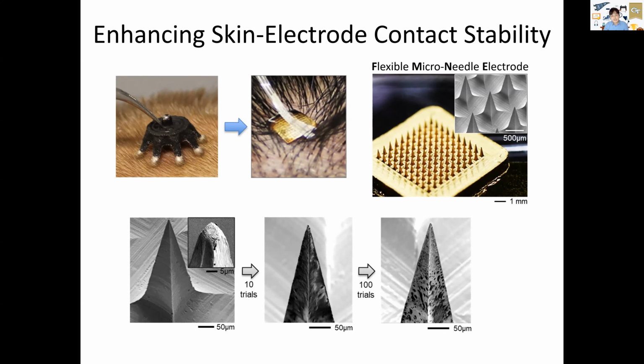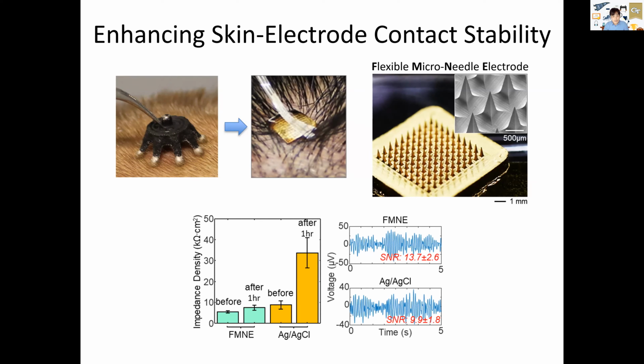And this microneedle can be reusable multiple times to measure EEG. The main advantage of this microneedle electrode is that it can maintain the impedance density over the course of multiple hours, shown as green bars. When you compare that with the conventional gel-based electrode, you see the conventional electrode has huge degradation after 1 hour. So that's why you can use this dry microneedle electrode to maintain the signal quality.